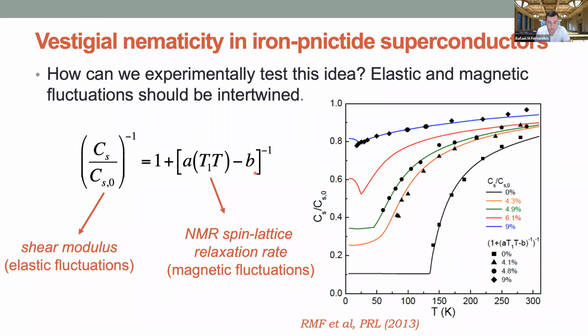And then again, you derive this relation. Now you can measure both of them separately, the shear modulus and T1T, and you can see if they satisfy this relationship, and they do satisfy it pretty nicely, as shown in this paper. This was for one compound, and later the group of Anna Böhmer and Christoph Meingast extended that to other compounds as well. So this shows that the elastic fluctuations are intertwined with the magnetic ones.